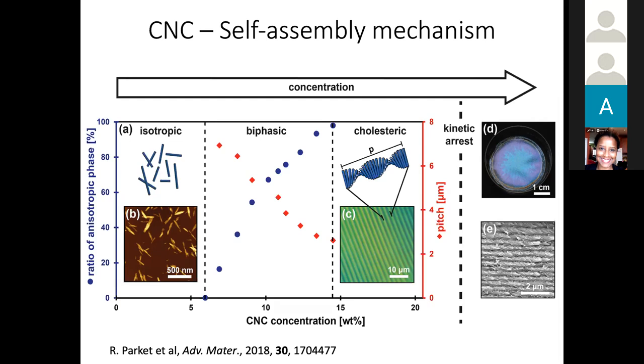They are nanoparticles that are charged, but when you put them in suspension and you increase the concentration, they start to interact and form what is called a cholesteric chiral nematic phase, where they form an architecture that is actually really analogous to what I was showing you in the plant. So this is, I would say, not a full coincidence, but the mechanism that regulates the cellulose in the plants and the cell wall is completely different from what's happening here in a colloidal suspension. But the architecture is the same.